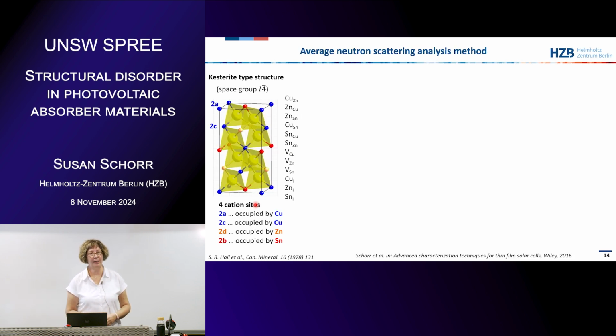And for that we developed what we called the average neutron scattering length analysis method, and I will just give you a brief introduction to how we do that. This is just to show you the kesterite type structure here. You see this tetrahedrally coordinated sulfur. In kesterites it's always 2 copper, 1 tin, 1 zinc around it, and we have in the kesterite structure 4 different cation sites. So this is the way the kesterite structure is defined, with the space group I-4 and these 4 cation sites. This is not my idea to call them 2a, 2c. These are the Wyckoff positions, and you maybe learned it a little bit in crystallography. Each space group has a number of Wyckoff positions which can be occupied by different atomic species.